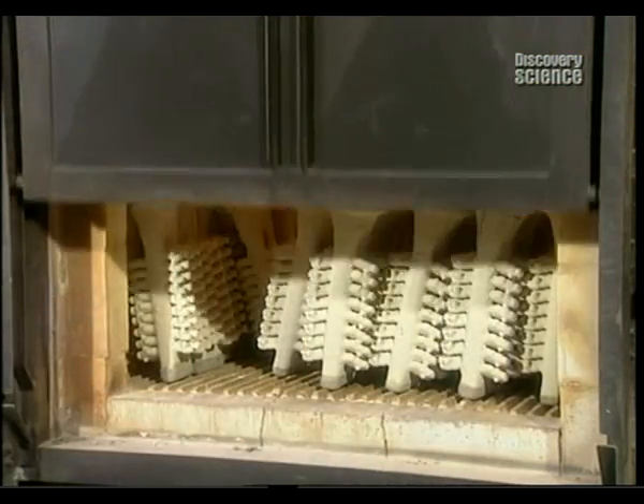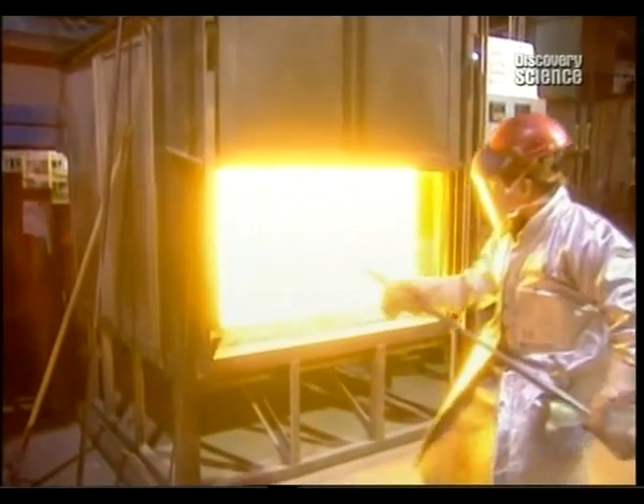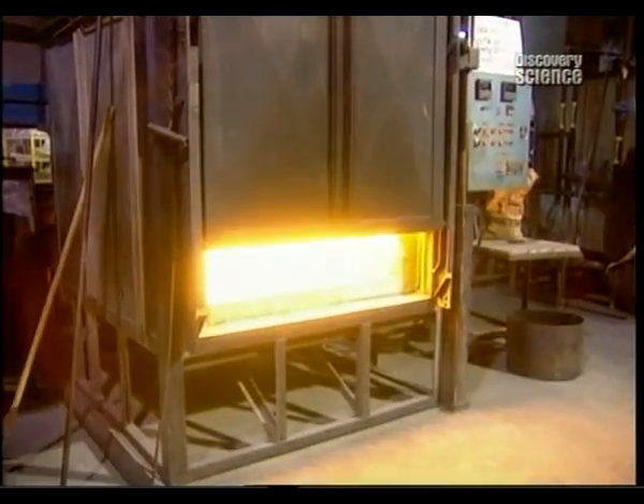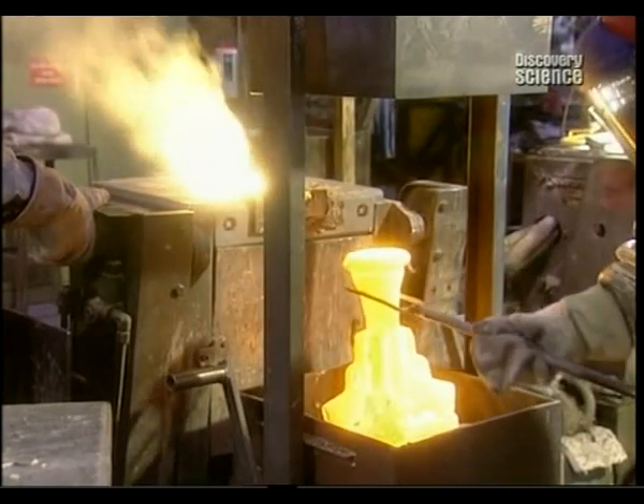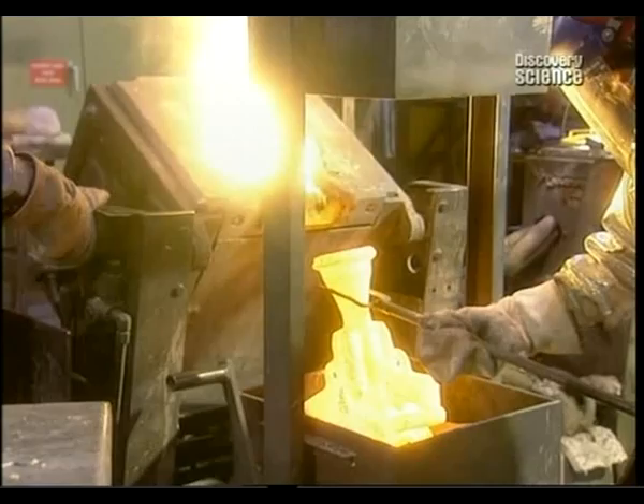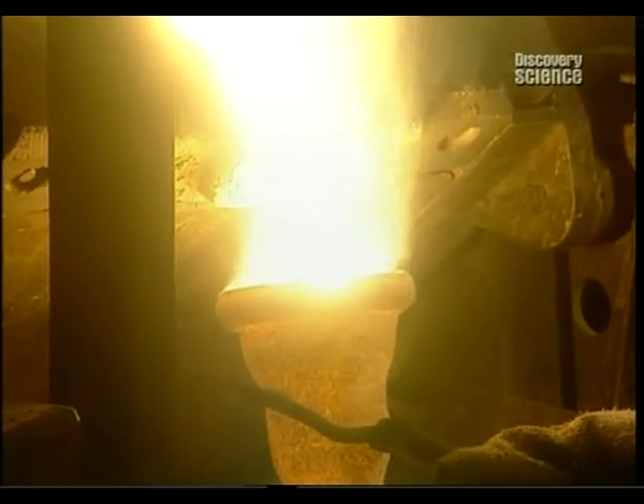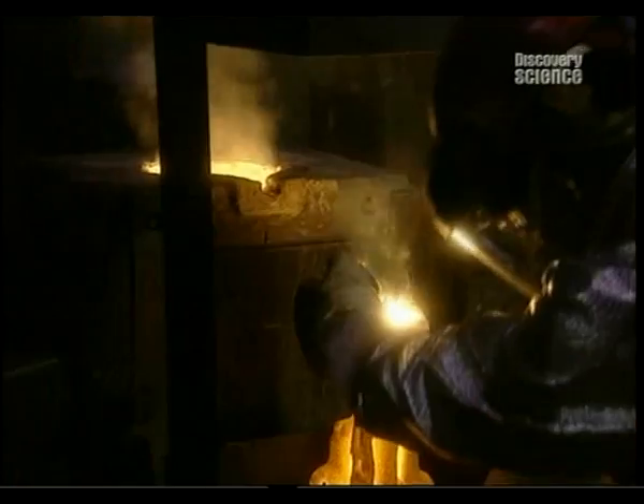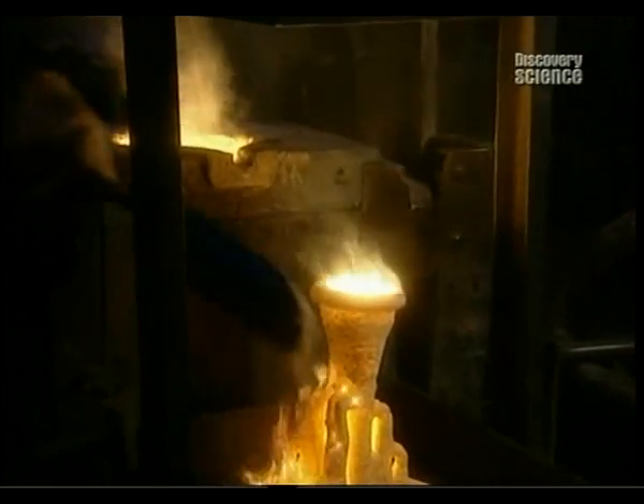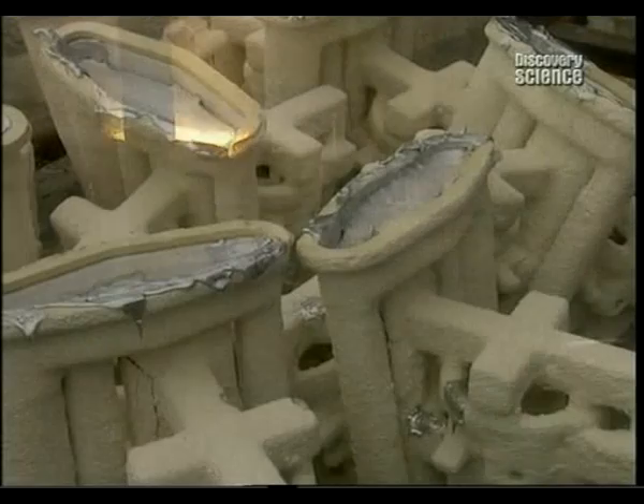First they put the cold mould into an oven and heat it up for 2 to 3 hours. This prevents the mould from cracking from the shock of coming into contact with molten metal at a scalding 1200 degrees Celsius. Molten metal is poured into the mould's cavity, which then cools and hardens at room temperature. That takes 2 hours for aluminium, 4 to 5 hours for steel.